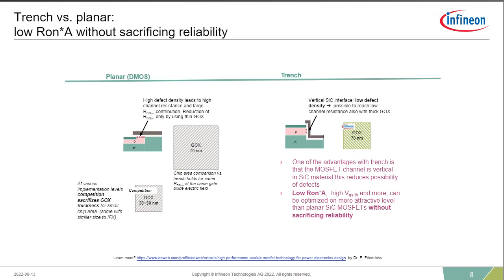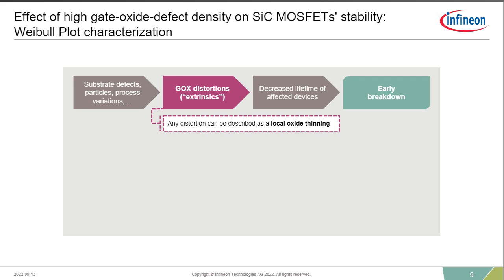There are challenges, however, of having a lower gate oxide thickness, and this particularly comes into dielectric breakdown of the device and creating extremely high field strength on the device, which can lead to premature failure. And we'll see as we transition through the slide, particularly the impact that has with respect to extrinsic defects and being able to filter those out in the manufacturing process.